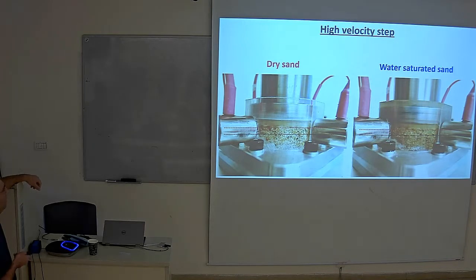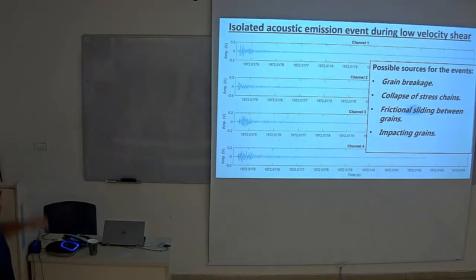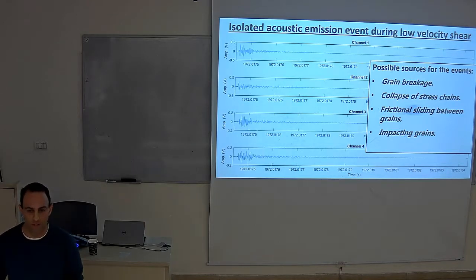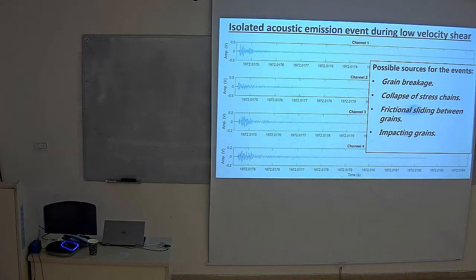Okay. So maybe we can find the answer for the difference in the acoustic emission measurements. And the acoustic measurements look like this. This is an amplitude in voltage versus the time of the experiment. And we see waveforms, and we can actually detect the first arrival in the red X here. And then we get the small earthquakes, and that is getting back to the noise level.